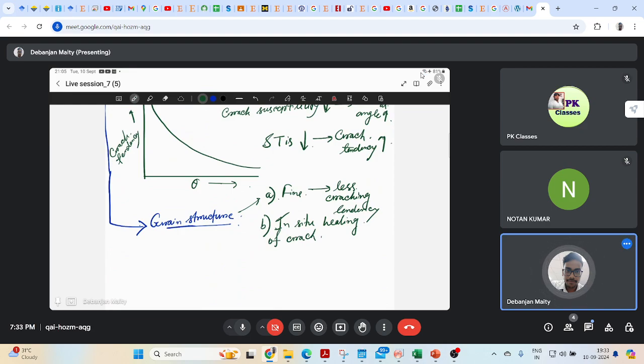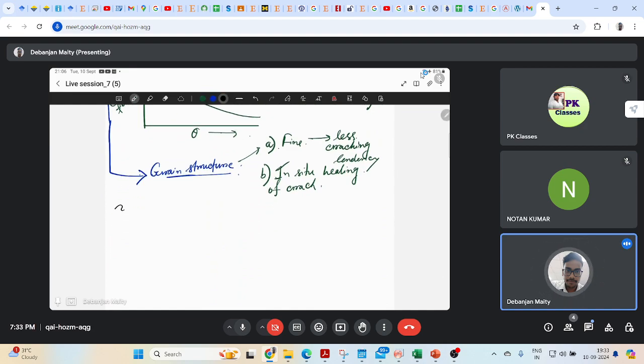Any idea of what is liquefaction cracking? This is solidification cracking, based on thermal contraction and those things. What is liquefaction cracking? This is also called hot cracking. So write it down, something called liquefaction cracking. If you have the presence of low melting phases at grain boundaries that liquefy during heating, that will result in cracking upon cooling.